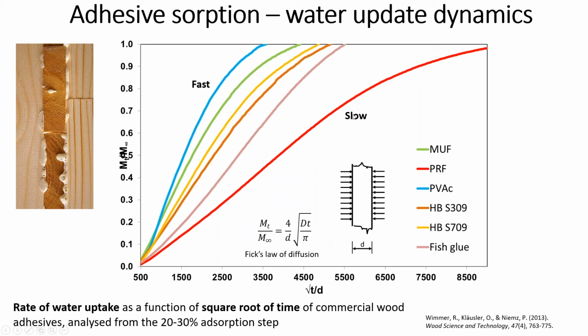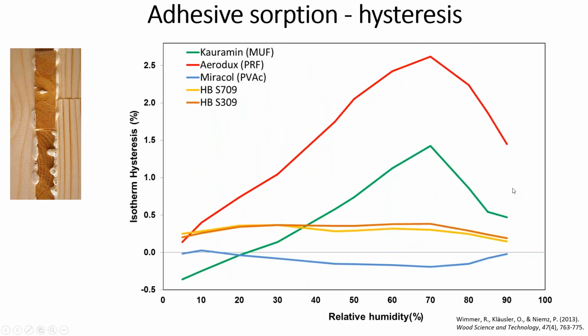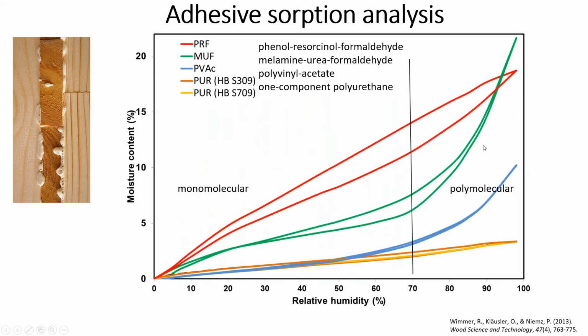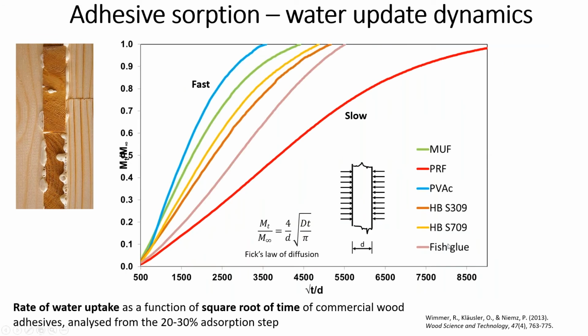And the quite interesting result was there were slow diffusing ones and fast water uptaking ones. And the ones that were slowly responding to water change, like the dynamics of water uptake, were those which tended to be highly absorbing water. So when it comes to the historical fish glue, it's actually behaving better in terms of slowly responding compared to the phenolic resorcinol formaldehyde. So this was teaching me that it's not just how much water gets picked up,